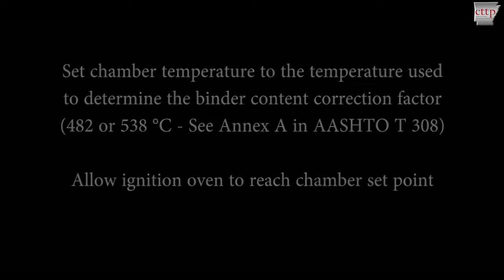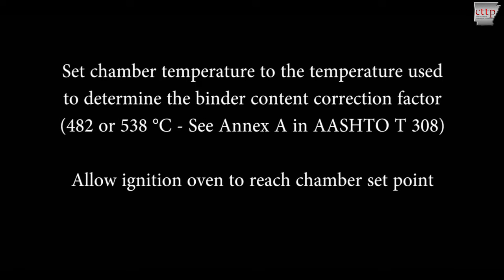AASHTO T308, determining the asphalt binder content of asphalt mixtures by the ignition method. This video demonstrates the determination of the asphalt binder content of a plant-produced asphalt mixture using an NCAT convection ignition oven. Turn on the ignition oven and set the chamber temperature to the temperature used to determine the binder content correction factor, which is either 482 or 538 degrees Celsius. See Annex A and AASHTO T308 for more information.